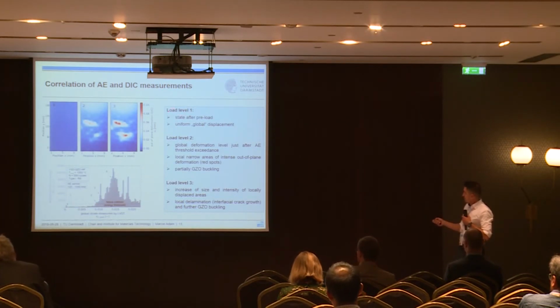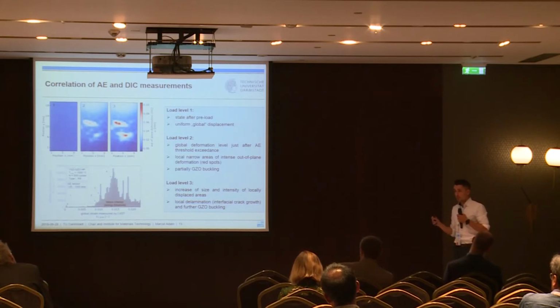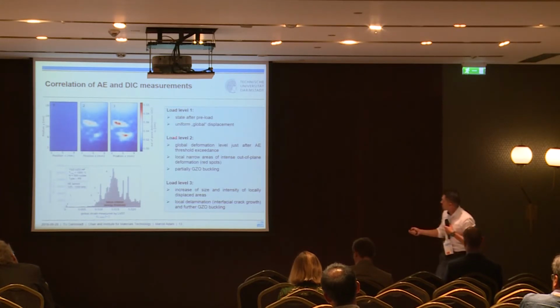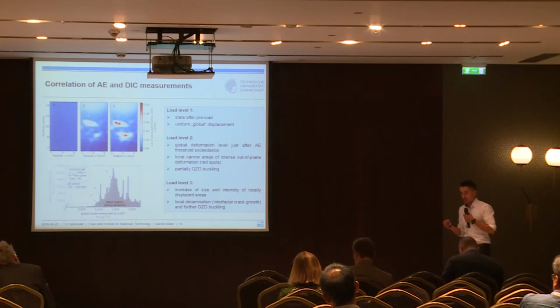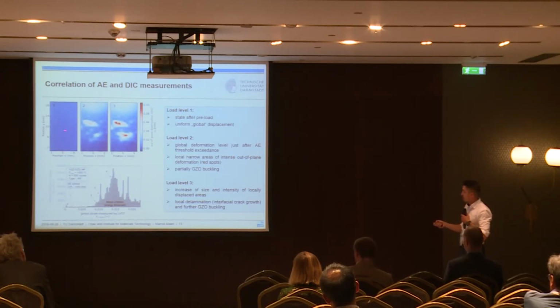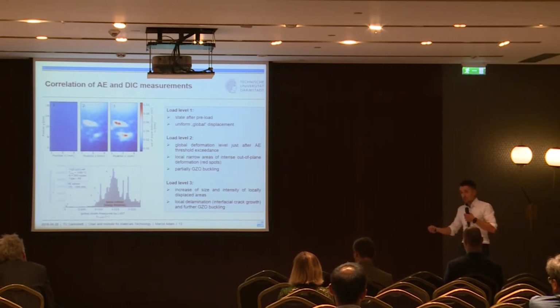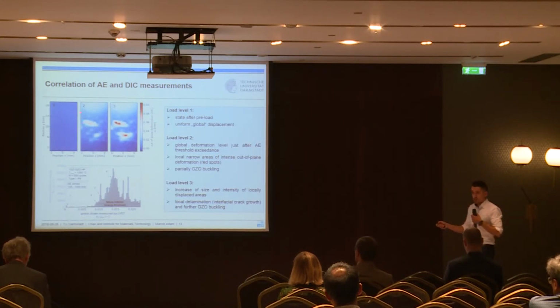At point number 1, load level number 1, this is the stage directly after preload. We have a uniform global displacement. Here I should mention we see the out-of-plane deformation, which means the radial deformation of our specimens. So in load level number 1, we have a uniform global out-of-plane deformation, and if we increase the load and go into load level number 2, which is the load level directly after the TBC is going to fail, then we clearly see local narrow areas of intense out-of-plane deformation. We can call them red spots maybe.